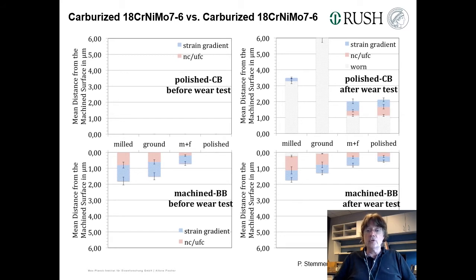Certainly there was a little bit of wear, so this is gone. And then you find your shear band, the tribological material, mechanically mixed, and then you find the strain gradient. But this is overlapping this one. It is the same for the ground as well, for the milled and finished. So here you cannot really say that this comes from tribological interaction. It has been there before.